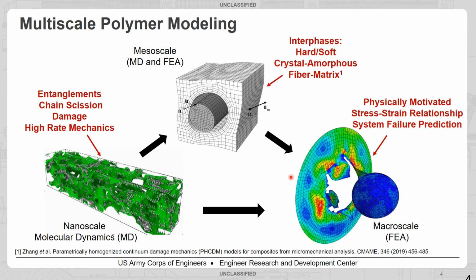So we want to be able to use multiscale modeling in order to investigate some of these effects. Here we use MD simulations to look at the nanoscale behavior of things like loss of entanglements, bond breaking, damage, and in general just high strain rate mechanisms. We can use that to either inform directly a macroscale model or go through a mesoscale to look at things such as fiber matrix bonding, hard, soft phases, interfaces of crystal amorphous regions. But the overall goal is to use this information that we gather at nanoscale and mesoscales to bridge the macroscale, either in the form of rate equations or direct coefficients to put in macroscale models, so we can look at more structural things such as ballistic or blast penetrations that we see here.